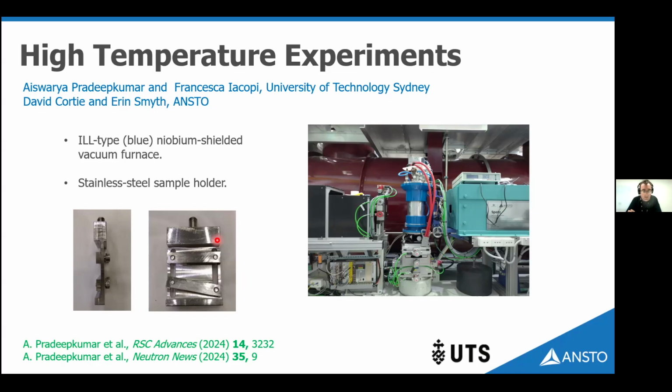So we have this stainless steel holder, and you can just clamp the sample into this. We have actually modified it a little bit because if you go to really high temperatures, you do seize the bolts, which makes getting the sample out a little bit difficult, especially if you want to keep the sample post-experiment. So now we just use tantalum wires to hold it to this sample.